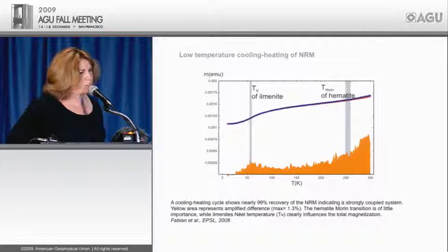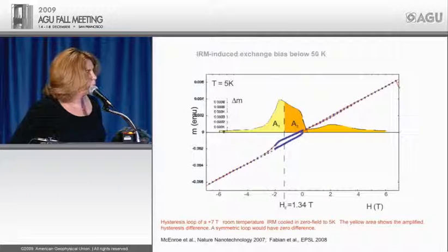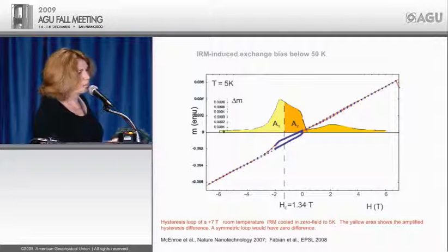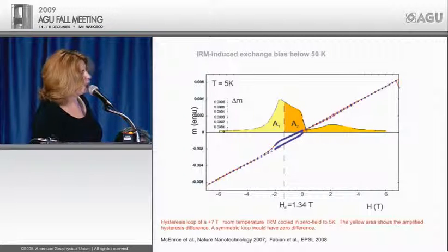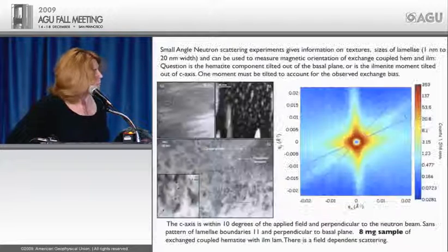The other thing I want to mention about the hysteresis loop is other experiments we did. We took the natural material without applying a field and just took it right down to 10K and ran a loop, and it was shifted. And what that tells you is the NRM itself is causing the shift.